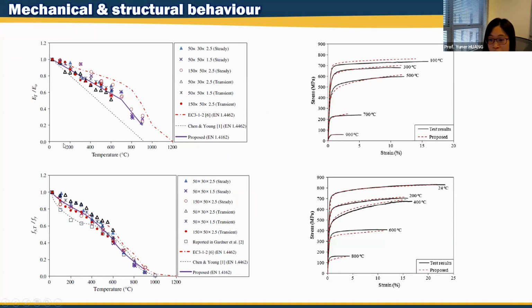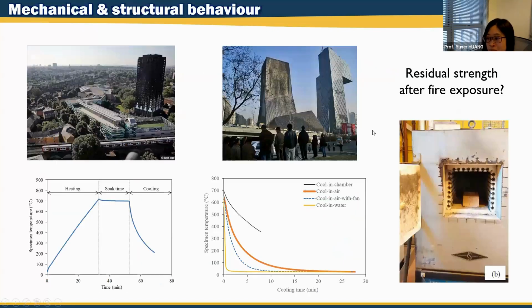We can see that if we plot the horizontal axis as the temperature and the vertical axis as the reduction of Young's modulus and the yield strength, the current design rule, which is the red line and the dotted black line, cannot predict lean duplex stainless steel very well. So in our research, we propose a new curve specifically for lean duplex stainless steel. Using this curve, we can predict the reduction in property under different temperatures. And we also propose design rules in order to predict the full stress strain curve for lean duplex stainless steel.